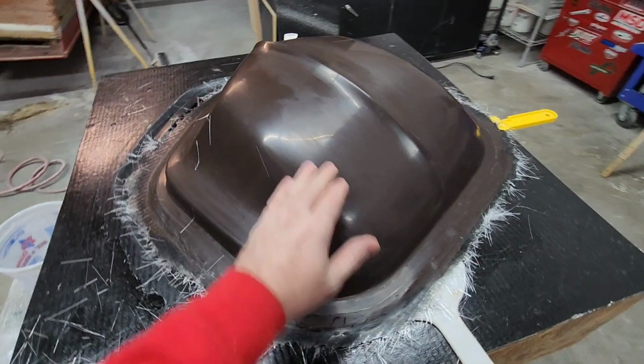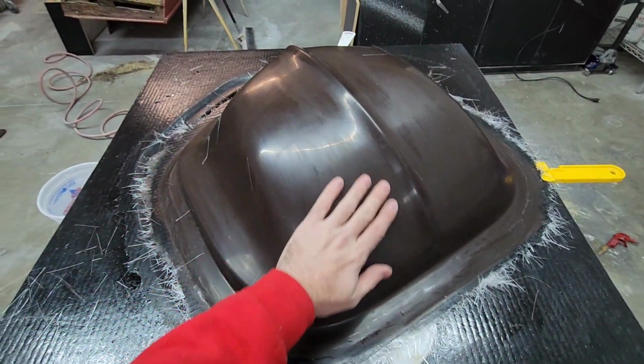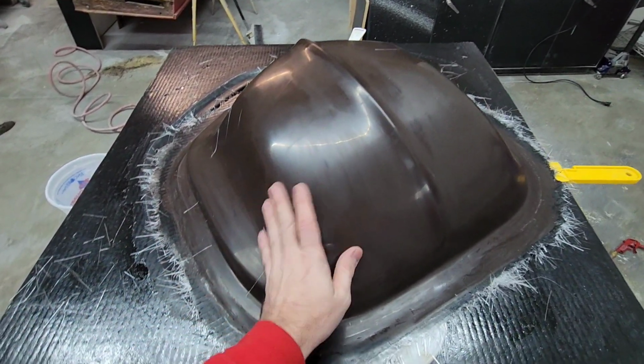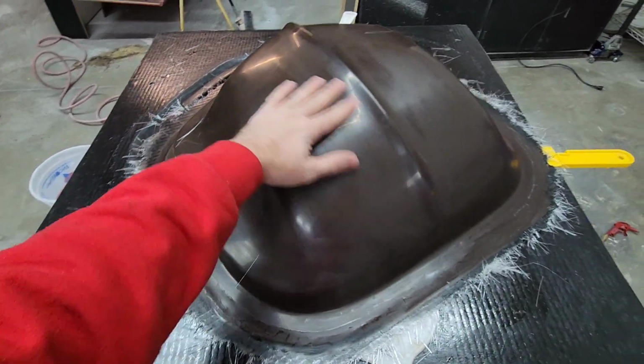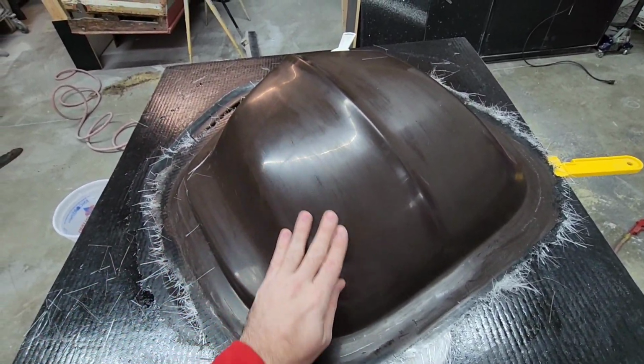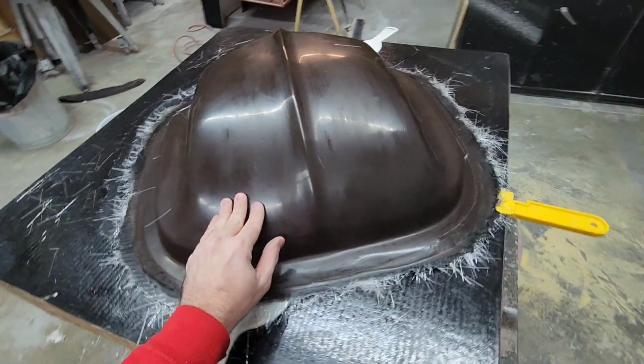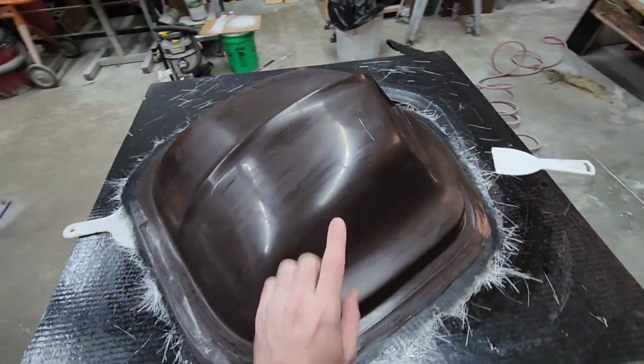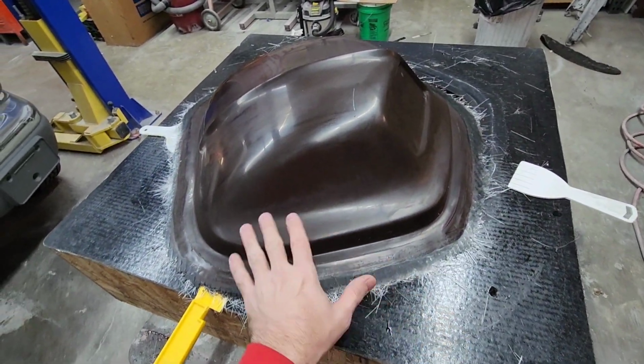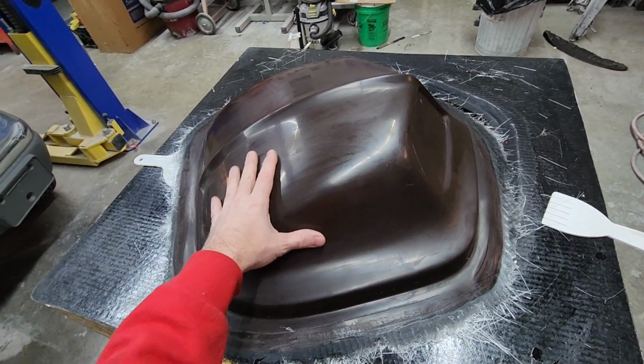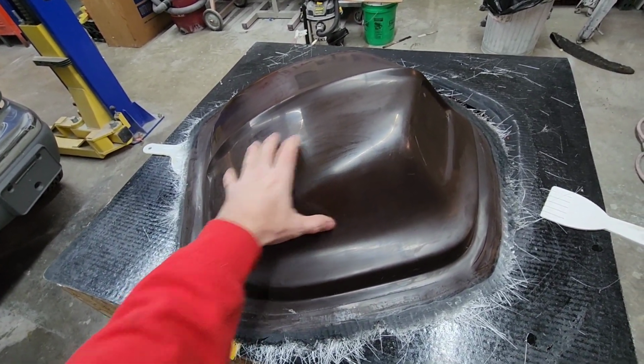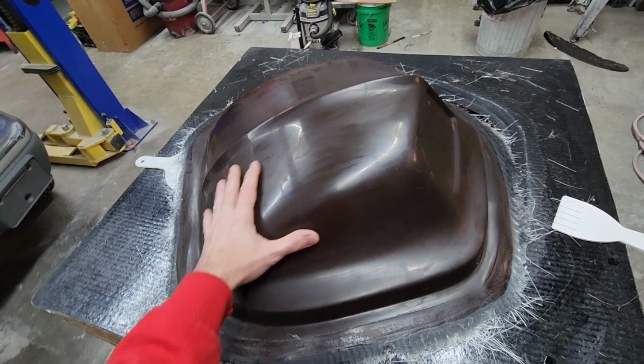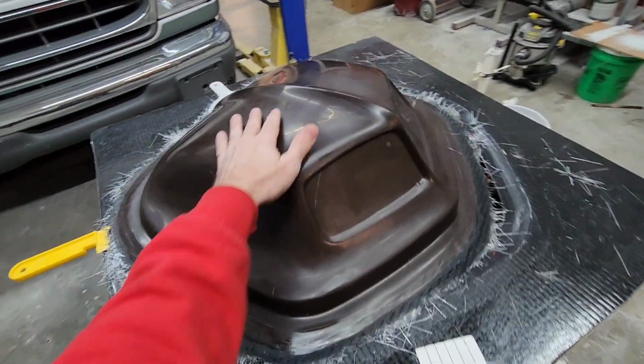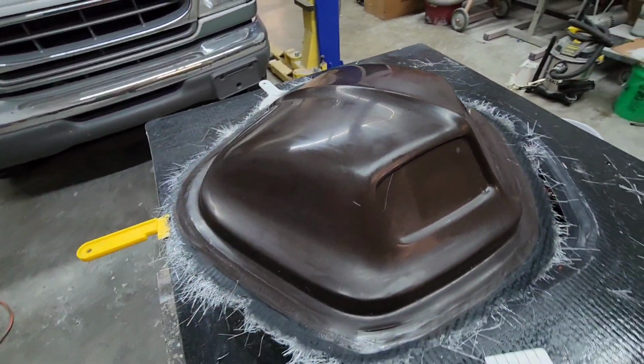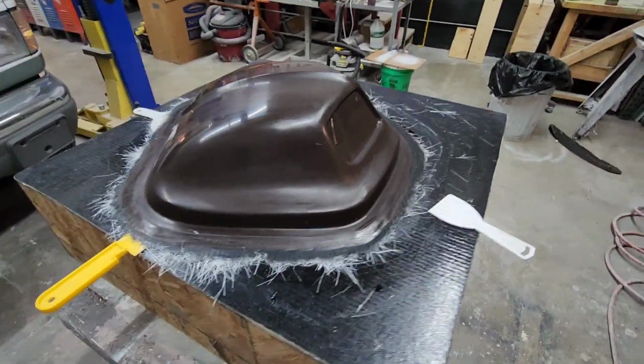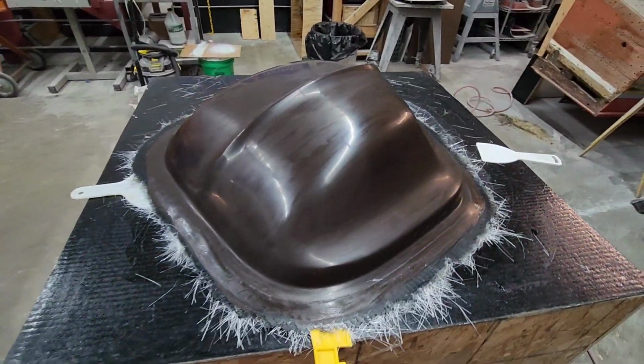So you can see this has a little bit of a dull surface finish. Now that's due to 2 things. 1, the PVA, you know, it doesn't leave the shiniest surface. And 2, our mold isn't super highly polished since this is just a fiberglass mold. If this were a carbon fiber mold, we'd have it polished a lot better, because this is going to be the finished product. On this one, you know, these get sanded and painted. So this is a perfect finish for coming out of this mold. So there you have it, step by step, how to produce a part from a mold.